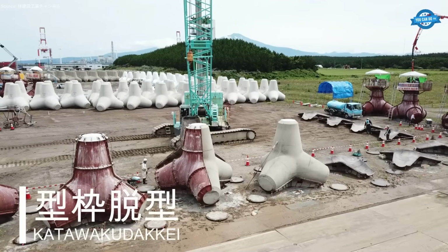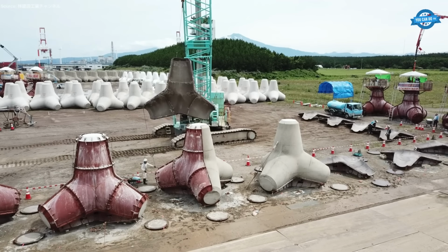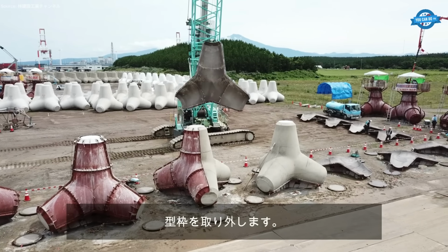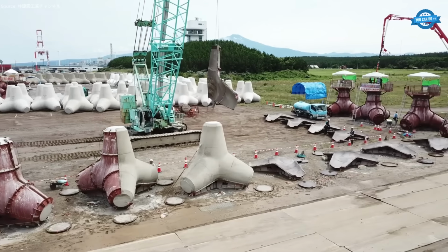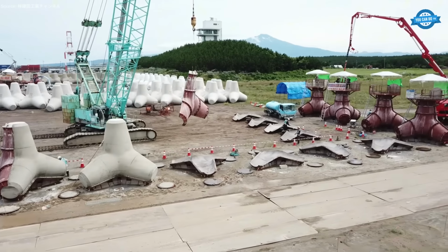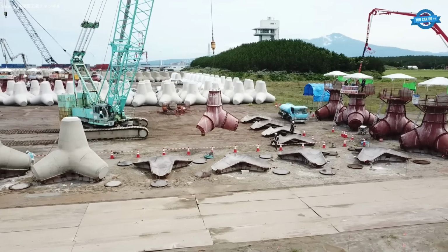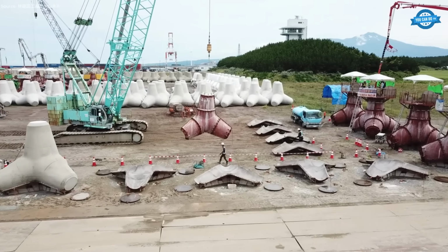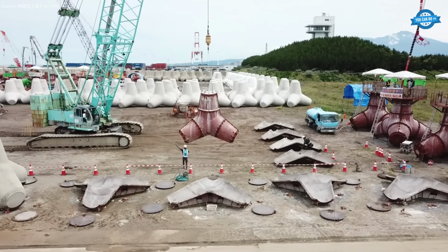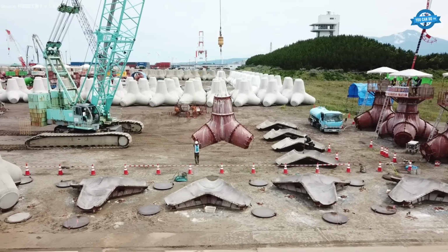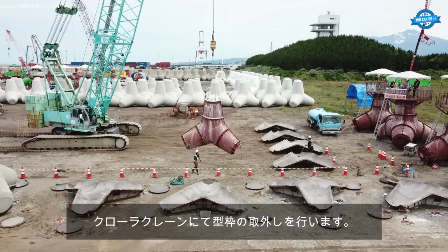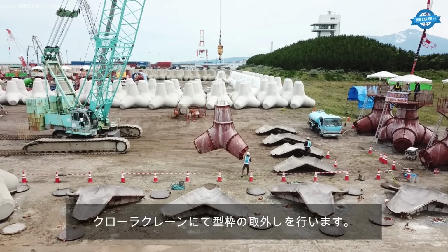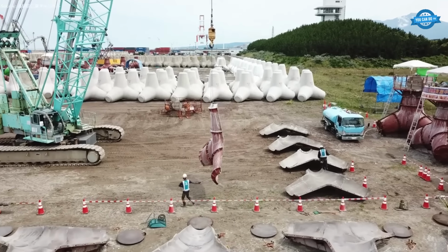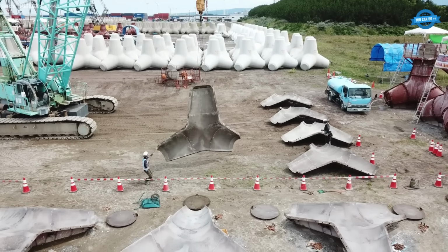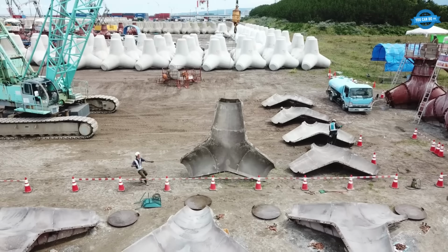After sufficient curing, the formwork is dismantled with a crawler crane. Each formwork panel is brushed clean for reuse in the next cycle. The newly demolded tetrapod undergoes membrane curing, where liquid agents form a protective film, reducing evaporation and enhancing strength development. After several days, water testing confirms the surface integrity. The result is a fully completed tetrapod, ready for coastal installation, where it will serve as a durable structure against wave energy.